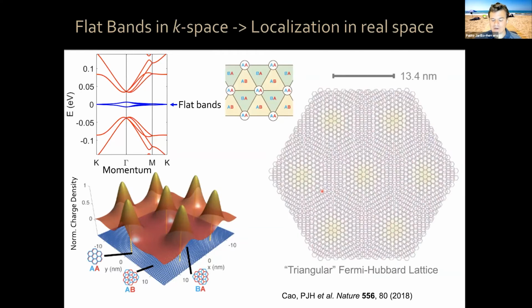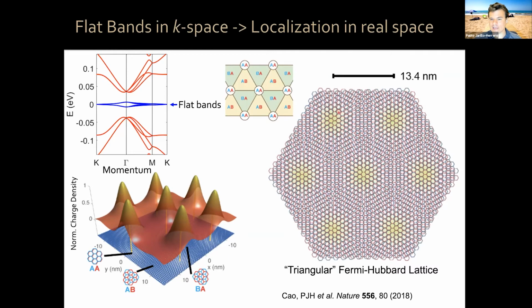So in a slightly more realistic schematic, these regions of AA stacking are spaced by 13 nanometers at 1.1 degree angle, okay? And this forms the equivalent of a triangular Fermi-Hubbard lattice by analogy with the cold atom systems, except that it's triangular in quotes because in reality, this is a honeycomb structure because of these AB and BA regions. And also, this structure has interesting topological properties, as I will mention in a moment. So it does not really offer a direct mapping to a standard Fermi-Hubbard lattice that you can isolate into isolated atoms. This actually has topological properties that prevent that direct mapping.